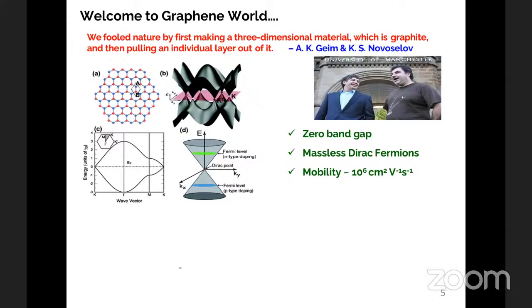But in graphene, the Schrödinger equation fails to explain the properties behind the band structure of graphene, because the electrons in graphene behave in an unusual way that cannot be explained by the Schrödinger equation. Instead, the Dirac equation is usually applied to explain the band structure of graphene, because this band structure is highly linear, which is usually observed only in relativistic particles such as neutrinos. Okay, and graphene is a zero-bandgap semiconductor, or you can even treat it as a semi-metal.